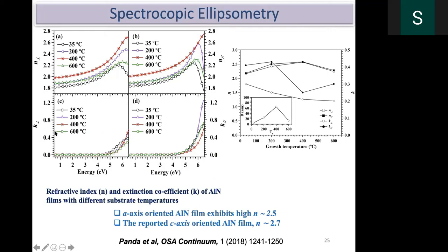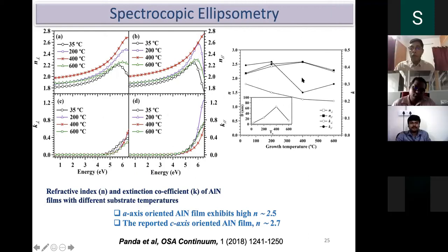the extinction coefficient, basically. When you test them and see that with the temperature, particularly the N component is increasing and decreasing. K component is not that much affected by this change of temperature. When you go to 400 degrees centigrade, probably because of the orientation, the N component is higher. When you see that reported C-axis oriented AlN film exhibited a 2.7 refractive index, but in our case, we have found around 2.5. Particularly the range of energy is around 6 eV. That is the one which I think 546 nanometer is the one normally people will compare for the refractive index is concerned.